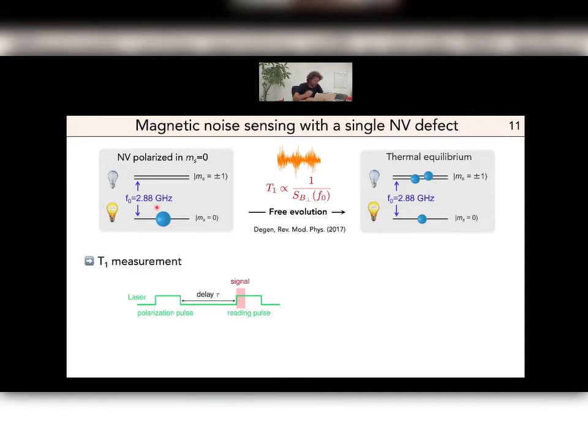So how do we measure this T1 with an NV? This is pretty simple. We just have a first laser pulse to polarize the system in ms equals 0. We are in this situation. Then we wait for a certain delay, and then we apply a second pulse, a readout pulse, that will read out the population of the NV defect through its spin-dependent photoluminescence signal.